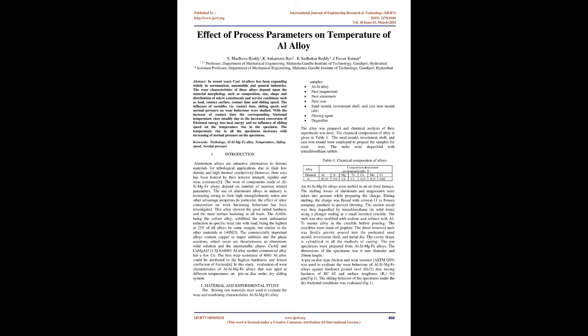The influence of variables, viz., contact time, sliding speed, and normal pressure, on wear behavior was studied. With the increase of contact time, the corresponding frictional temperature rises steadily due to the increased conversion of frictional energy into heat energy, and there is no influence of sliding speed on the temperature rise in the specimen. The temperature rise in all the specimens increases with increasing normal pressure on the specimens. Keywords: tribology, Al-Si-Mg-Fe alloy, temperature, sliding speed, normal pressure.